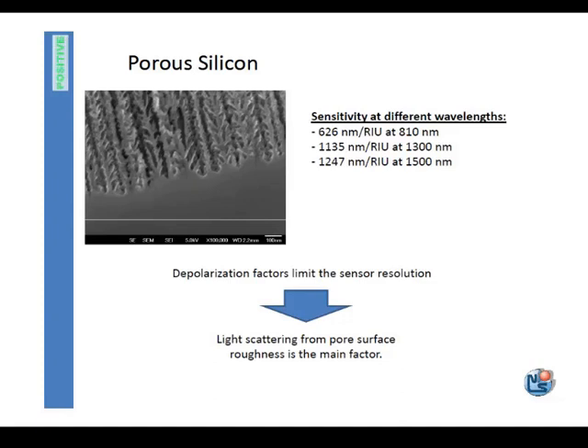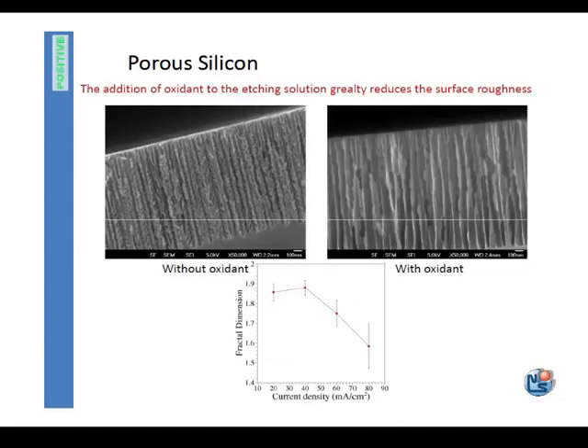But we noticed that the experimental response was much lower than the theoretical one. So we started to analyze the effect of these branched pores. And we see that the pores have a big effect on the depolarization of the light. So the roughness of the surface induces big light scattering that depolarizes the light and limits the sensitivity of our sample.